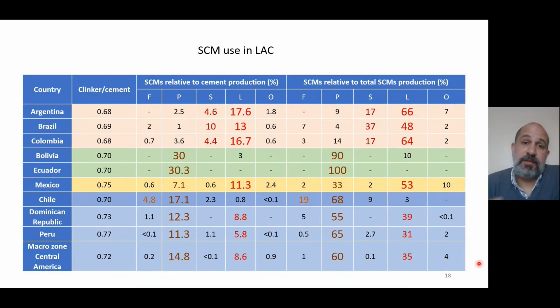When we have a look at the different SCMs that are used in different countries in Latin America, the previous cannot be generalized homogeneously for all regions. And then we have countries such as Argentina, Brazil, and Colombia, in which limestone is the main mineral mixture that is used for blending cement, followed by slag. And then we have a group of Andean countries such as Bolivia and Ecuador, in which pozzolans, natural pozzolans, are highly used, up to 30% of the total cement production.